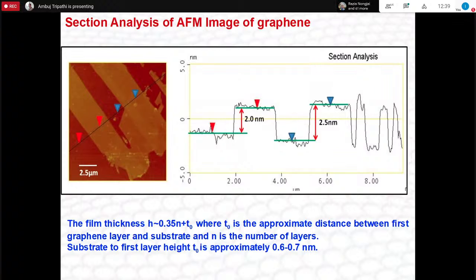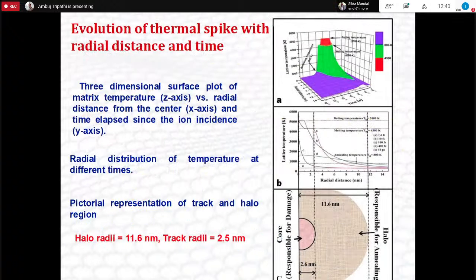So after irradiation, what happens is that we go back to the thermal spike calculation. And if you remember, during the school time, I had raised this point, and a response was given, because whatever we do, this thermal spike calculation, etc., is for bulk, but we had also tried to use this for 2D materials, in thin layers. And this is one of the examples, again using Professor Toulemonde's software for the thermal spike.